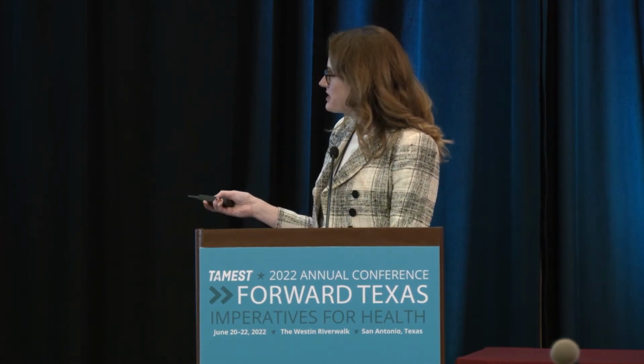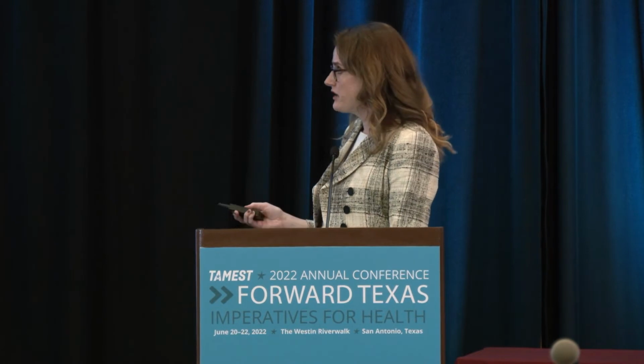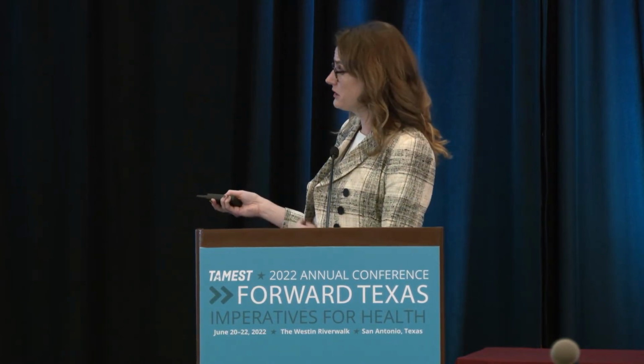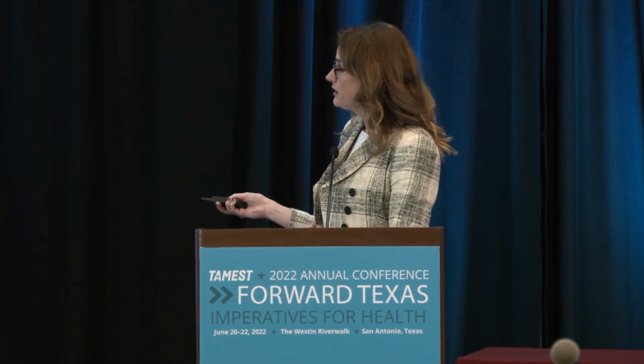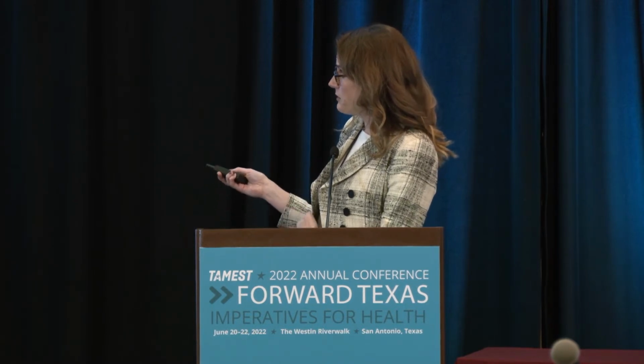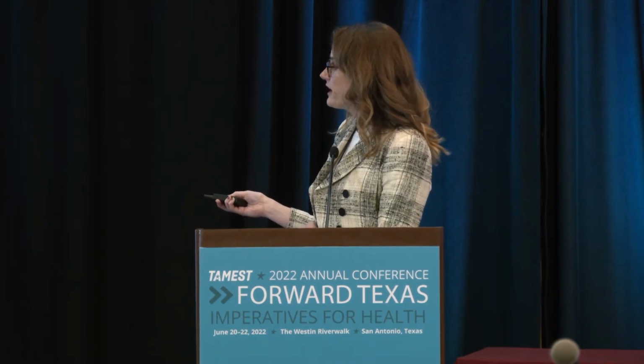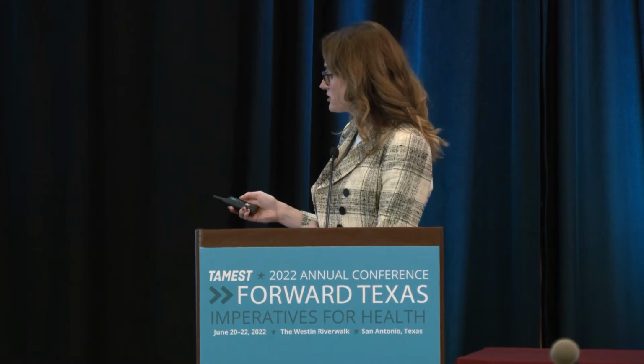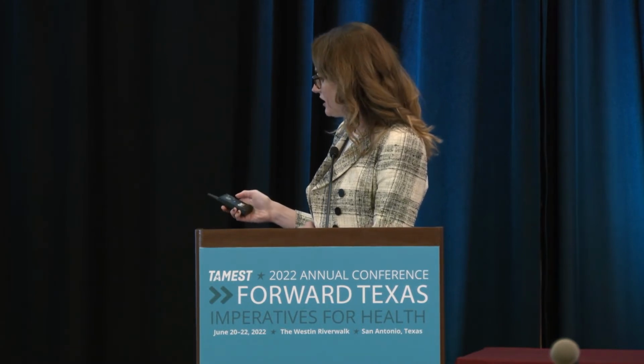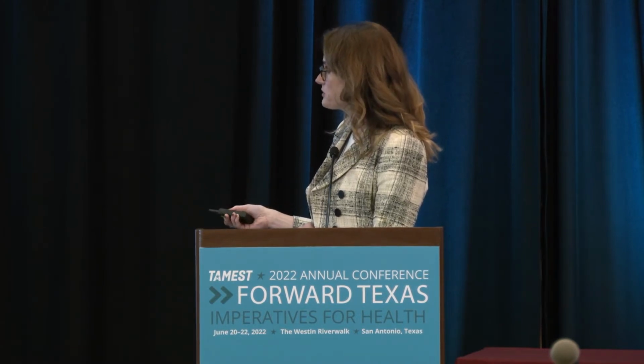The redox potential of this polymer is 3.6 volts versus lithium, so it's just a little bit lower than that of your lithium-ion battery. Its theoretical capacity is 111 milliamp hours per gram, which is, again, a little bit lower than your lithium-ion battery, but we can get really close to this theoretical value. And then this molecule in particular has a very high cycle life and fast charge and discharge. So this is just showing you can charge it in minutes and still get acceptable performance.